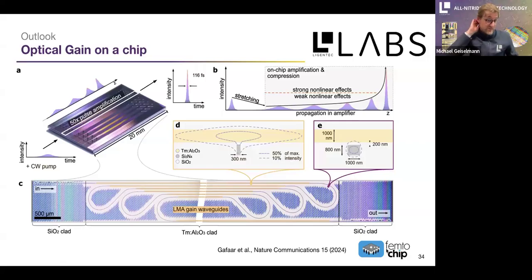And here in this paper, collaborators have shown a 50 times pulse amplification when you come in with your laser, and then have quite some centimeters of coverage where you again guide the mode in the nitride, but the mode sees the thulium doped aluminum oxide that is deposited on top, and like that you get a gain section over several centimeters, and at the output of the chip get a 50 times pulse amplification of your laser.